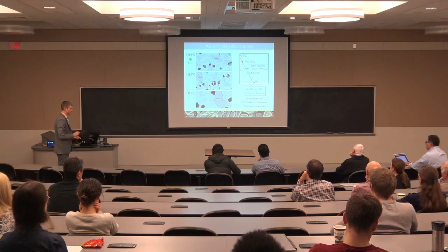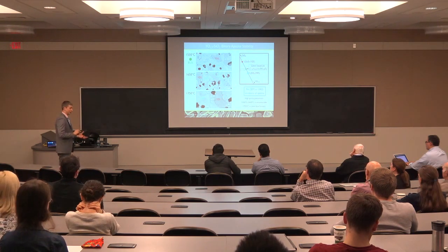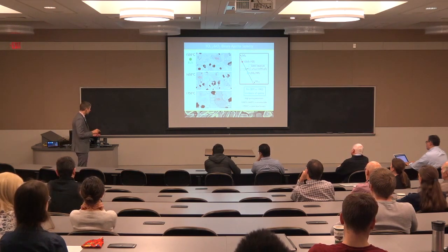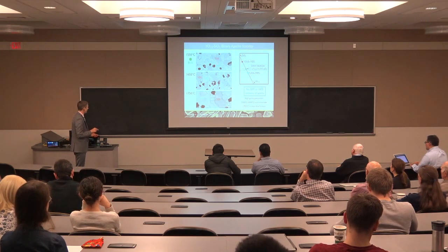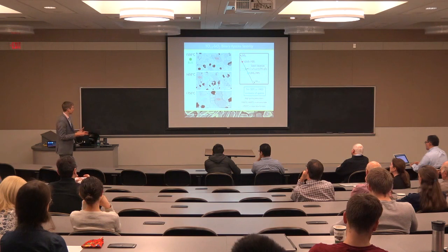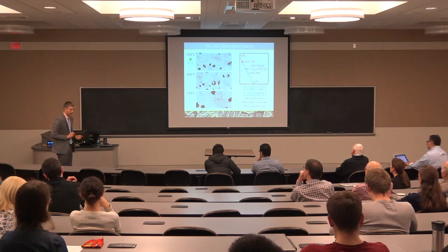This is a range of temperatures where it was suggested apatite might be stable. And in fact, we don't see apatite at all. We see disilicate and monosilicate. And I come back to this idea that there had been a suggestion that maybe apatite turned up out here.